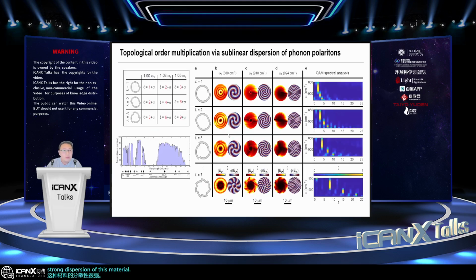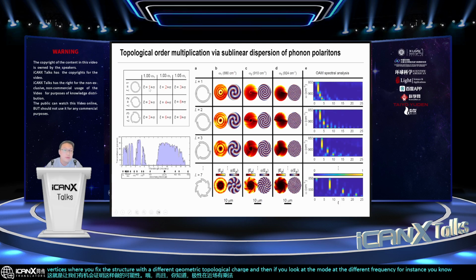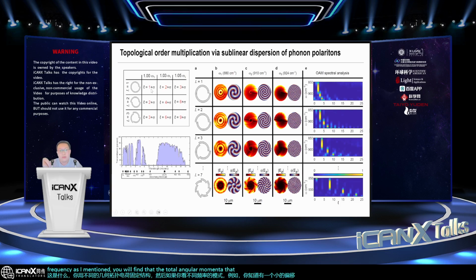And that gives us the opportunity to demonstrate the possibility of OAM multiplication in the near field for polaritonic vortices, where you fix the structure with different geometric topological charge. And then if you look at the mode at different frequencies, with a small shift of frequency, you will find that the total angular momentum, which carries of course spin and orbital components, behaves as if multiplied by the number of modes that you give as the structure.